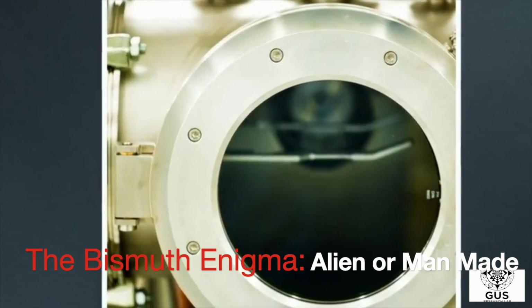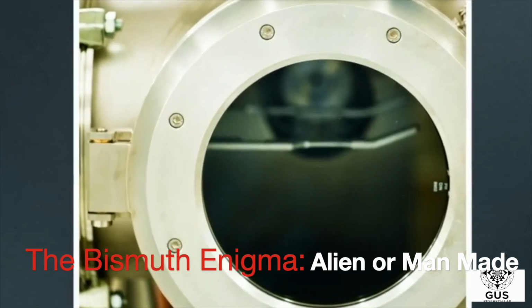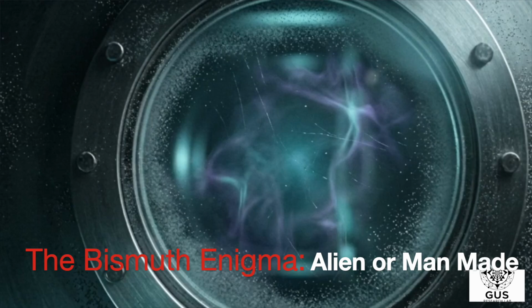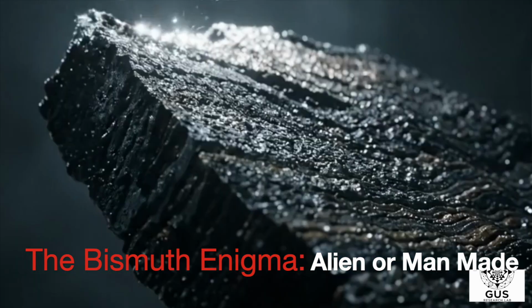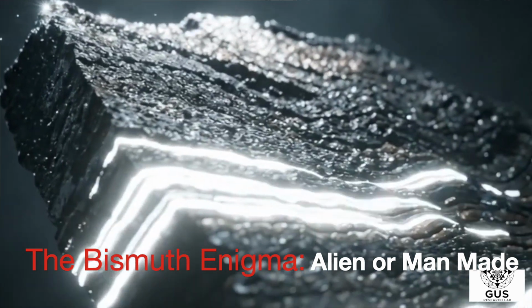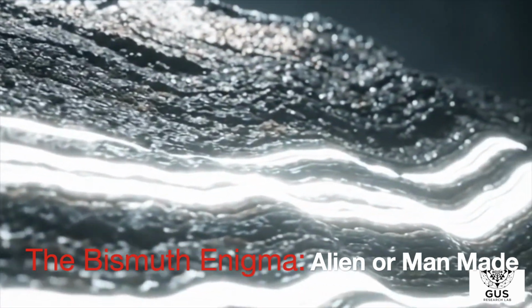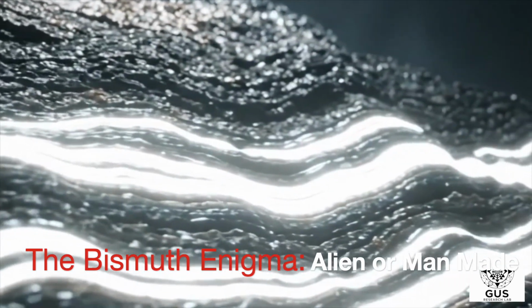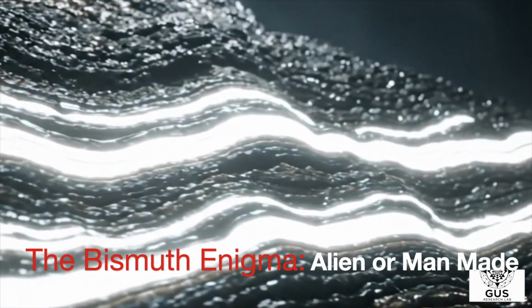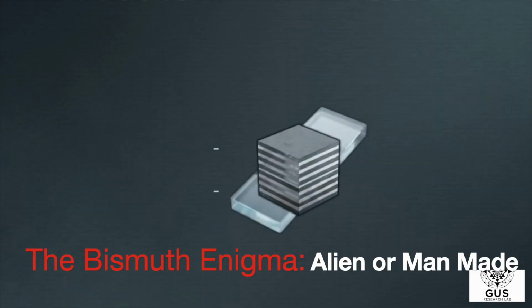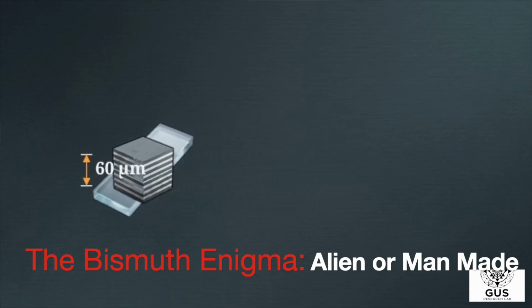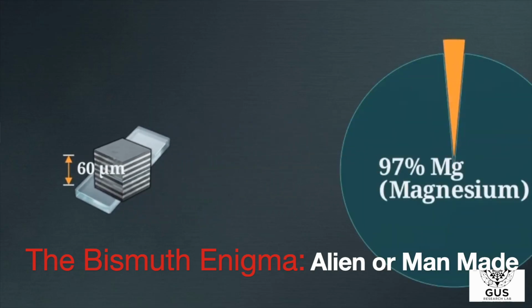In a vacuum chamber running both bismuth and magnesium targets, the metallic spray that misses its intended target lands on the chamber walls. After hundreds of hours of operation, these stray atoms build up into the same micron-thin, alternating layers seen in the mysterious debris. This reveals a critical blind spot in the extraterrestrial hypothesis. Advanced human industrial processes create highly complex, micron-layered metallic structures entirely by accident, producing industrial waste that mimics intentional atomic-level engineering.